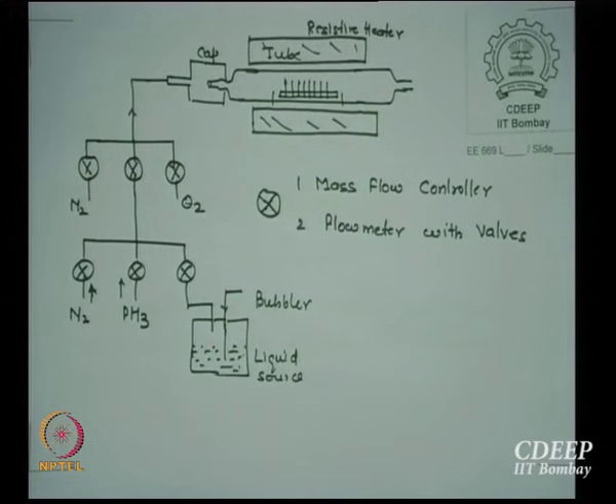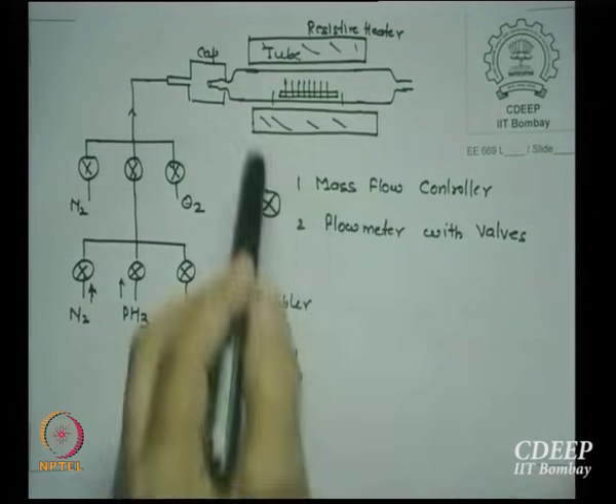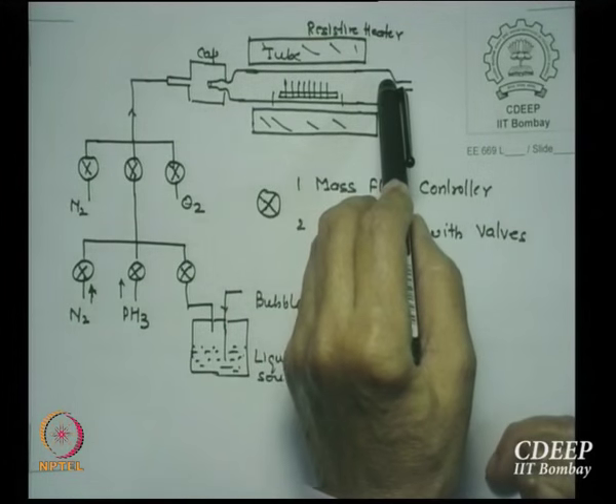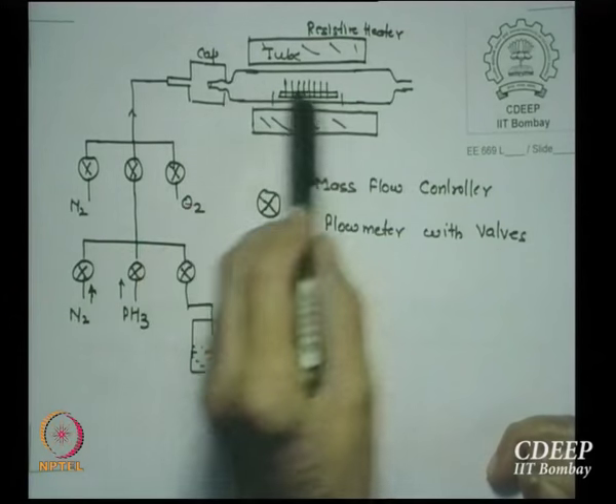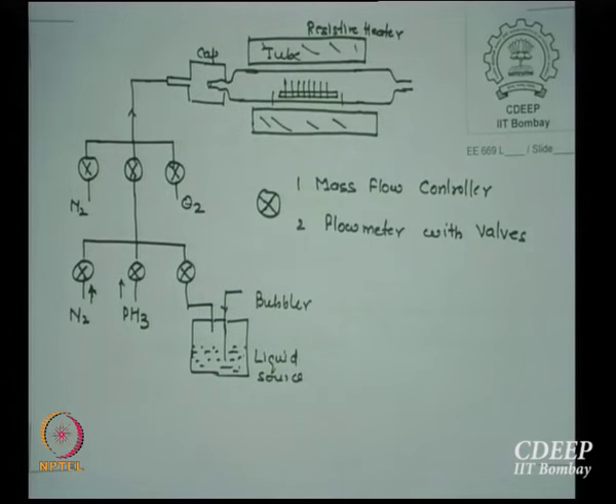So the center zone temperature should remain unaffected by the flow as well as by the change in your currents. So what they do is, you have end temperature monitoring, as well as center zone, three monitors. These are fed to a PID controller, and we keep on monitoring when to switch on or switch off the power to the coils, individual coils. And therefore, since PID controllers are very fast, we are able to control the temperature in the central zone to plus minus 0.25 degree centigrade.